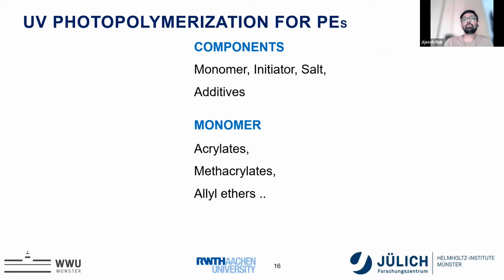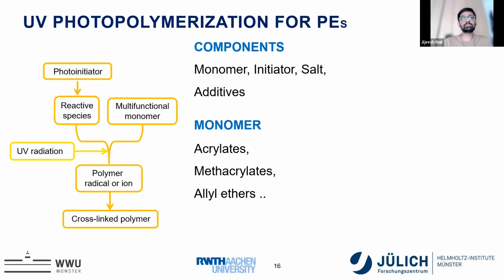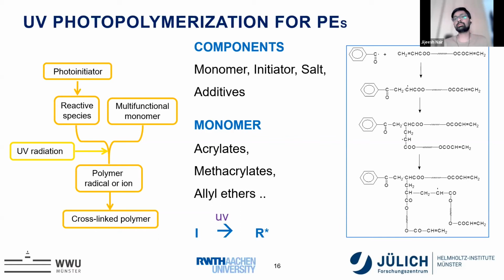And coming more to my work and my experience, it is UV photopolymerization, and to produce cross-linked polymer electrolytes, we use monomers, initiators, which is a polymerization system, and then salt and additives. And mostly as monomers, we use acrylates, methacrylates, or allyl ethers or allyl carbonates, etc. So in a simple system, we have photoinitiator, monomer, etc. We can mix these things together and UV irradiate it to produce a cross-linked network. So the initiator absorbs UV light, which will produce radicals. These radicals can react with the unsaturated bond, for example a double bond, and then it can continuously propagate this reaction to form a cross-linked network.